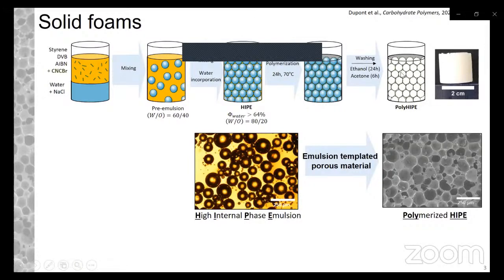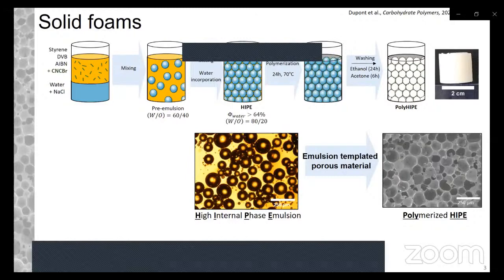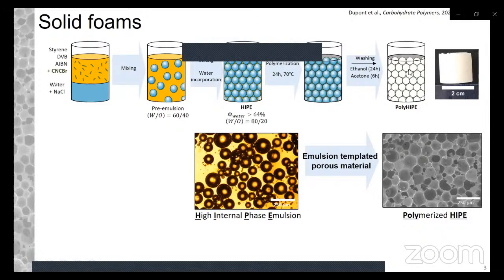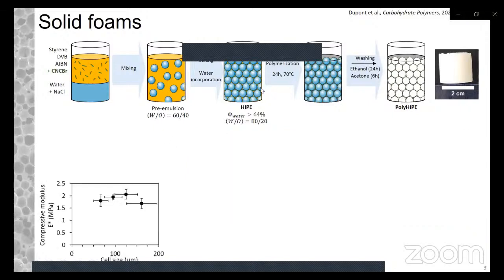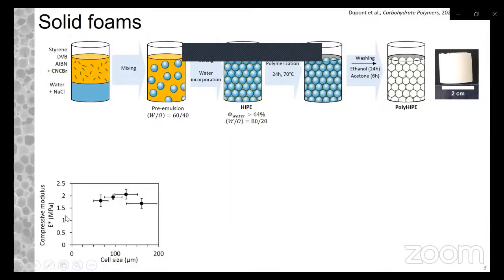By washing and drying, we can isolate a self-standing monolith, a porous solid, getting rid of the water and all the residual monomers. Here you can see by SEM that the polymerized HIPE is the exact image of the initial emulsion. Therefore, we can obtain emulsion-templated porous materials. We checked the mechanical properties of this material because the presence of the CNC might have an impact on them, as they have a Young's modulus of 150 gigapascals. By changing the diameter of the water droplets, we were able to measure different compressive moduli, but we found that there was no impact of the droplet diameter on this modulus.